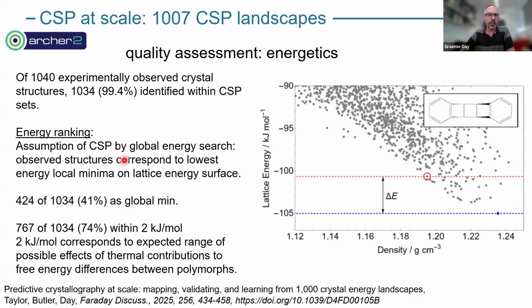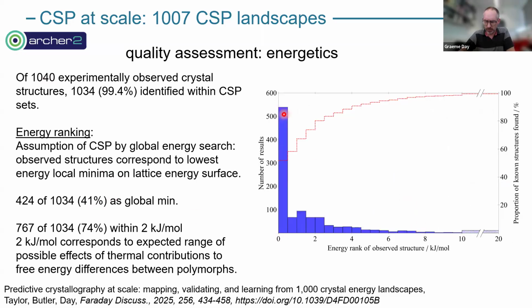In terms of energy ranking, observed crystal structures in over 40% of cases do map to the global energy minimum. So that's giving us validation of the energy model we've decided to apply. And if you look at this distribution of that delta E that we get, and this red line is a cumulative count here, if you look just up to 2 kilojoules per mole, then you're getting almost 3/4 of the observed crystal structures. So again, things are working very well.